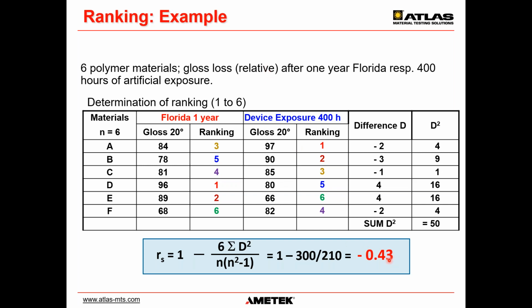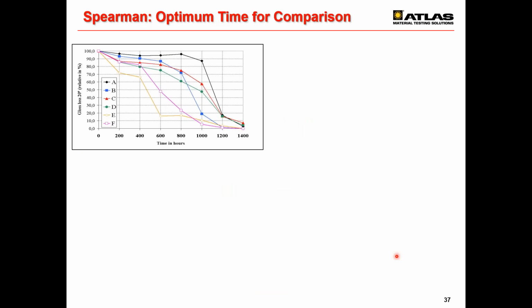Then you can simply calculate the Spearman correlation coefficient, and after 400 hours, the Spearman correlation is minus 0.43. So it's actually more or less a bad negative correlation. So definitely not the best time to compare it to Florida weathering.